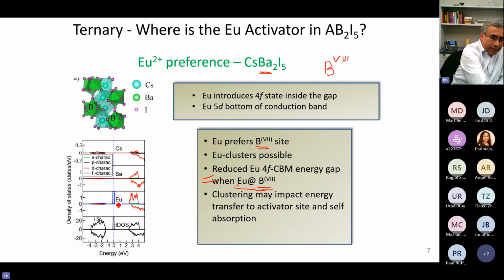You see them after you dope with europium. Europium has this right here. These are the half-filled F states of europium, and the remaining of the F states will be higher up in the conduction band, somewhere there. So when you dope with europium, that's what it is supposed to do. When it works like that, then we say europium is an efficient activator.